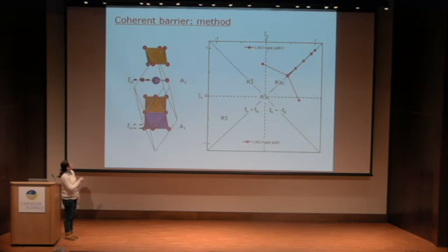But our only constraint is this structural constraint. And okay, we changed the constraint now. We see here, at the beginning of the path, the two lithium atoms move together and they stay on the high symmetry path. But starting somewhere here, this path deviates from the R3c, which means that these two lithium atoms don't move together. One of them, in this case the A2 cation, first penetrates the oxygen plane.